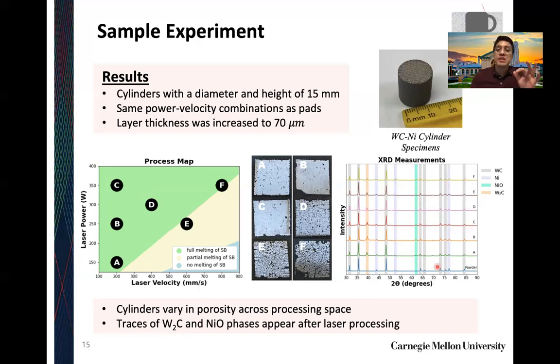Two things to note. There is a nickel oxide peak slowly getting bigger as you further increase the laser power, but it's not present in our powder, which is most likely due to the melting of our nickel and then having some of it react with the very small traces of oxygen in our chamber. So it's showing us that the laser processing is inducing a little bit of an oxide formation. Not too much to worry about. These peaks, at least the magnitudes of them, are still present even in a lot of sintering techniques as well.